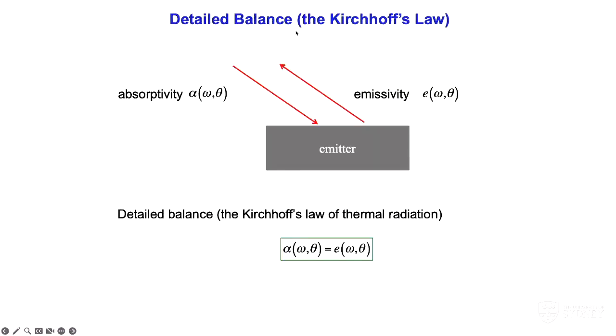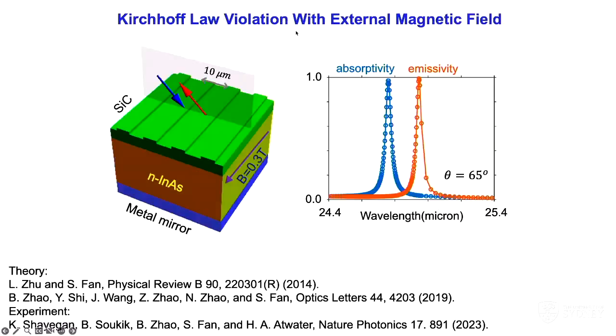So finally, one of the very important properties of a thermal radiator is something called the Kirchhoff law. And that says the absorptivity and the emissivity must be balanced in an angle by angle and frequency by frequency way. And as it turned out, this again can be broken. This is some of the theoretical prediction that we have done looking at a semiconductor material under a magnetic field. Again, in this case, with the presence of a magnetic field, you see the absorptivity and emissivity at the same angle and frequency split from one another. And this has been quite recently demonstrated experimentally in a collaboration with Harry Atwater's group.